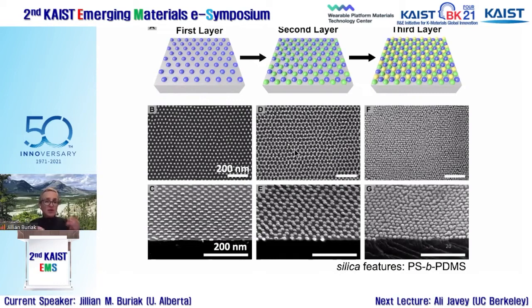So the particles or the dots underneath are large enough to force the block polymer above it, as it's self-assembling into a lower energy configuration, to have this registration. And then when we put in the third layer, the yellow, you get a triple density pattern. Okay, now